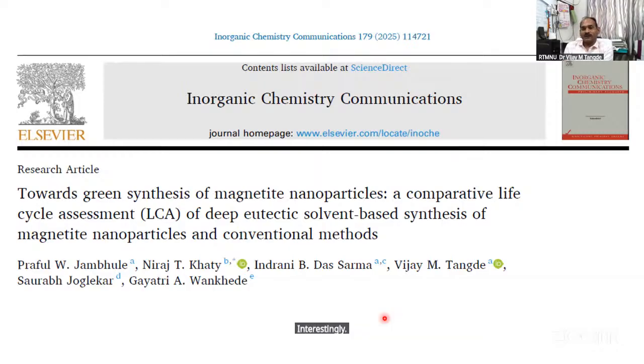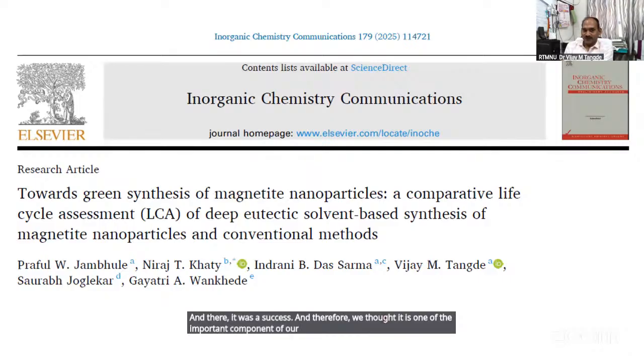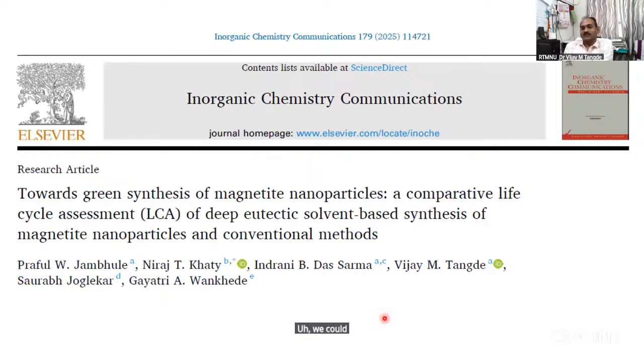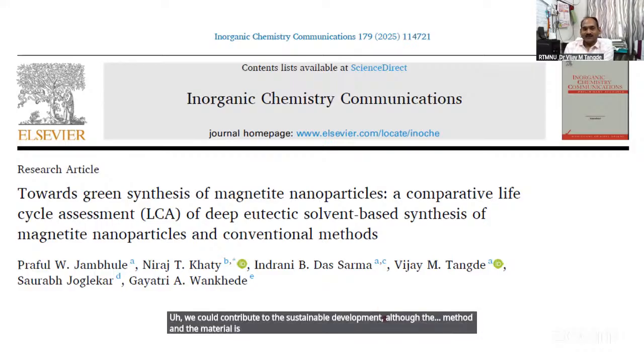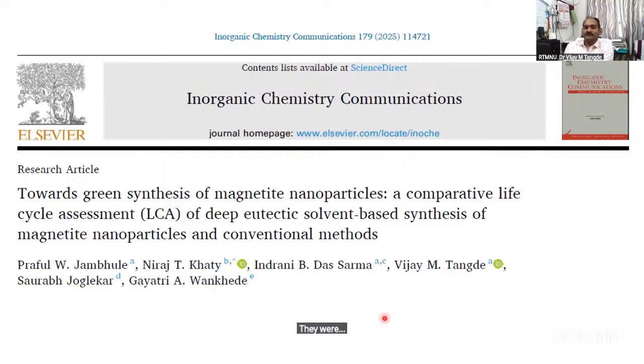Interestingly, we have reduced up to 60% of the environmental load compared to other conventional methods, and it was a success. And therefore we thought it is one of the important components of our laboratory wherein we could contribute to sustainable development. Although the method and the material are common, the way we have synthesized using the deep eutectic solvent is innovative. And that way, now the deep eutectic solvent is playing a role in the chemistry aspect. So I thought of sharing this study with you in that way.